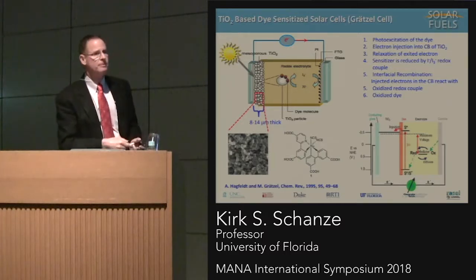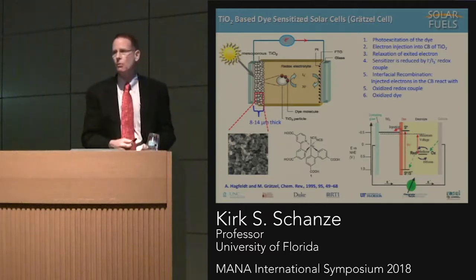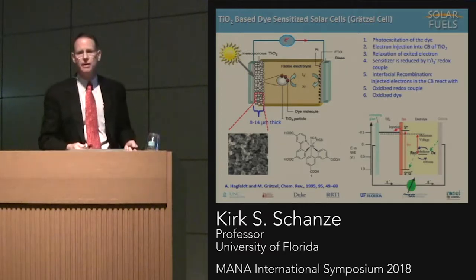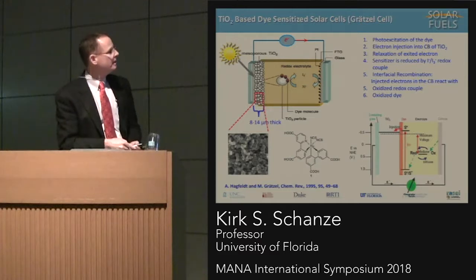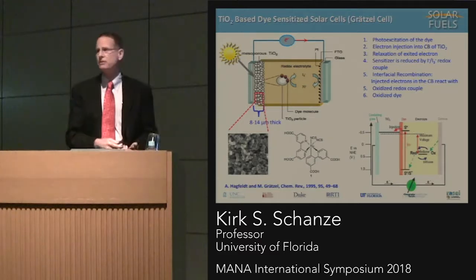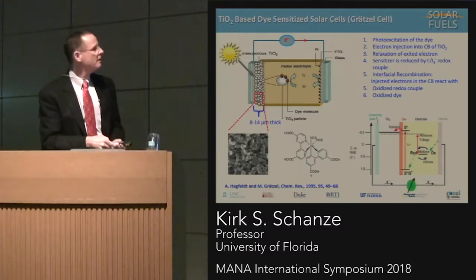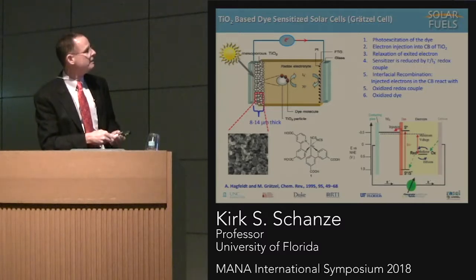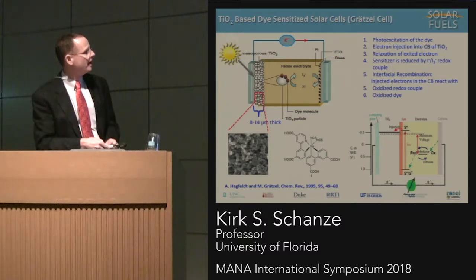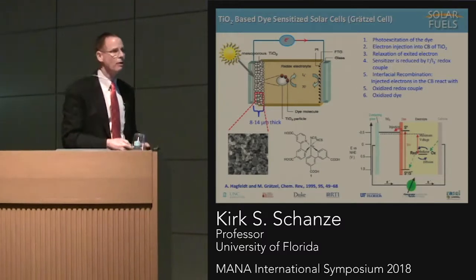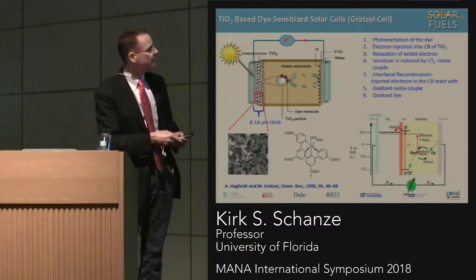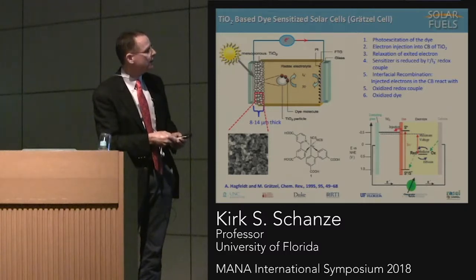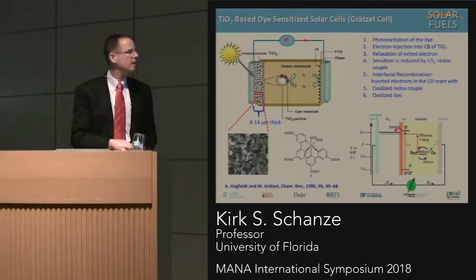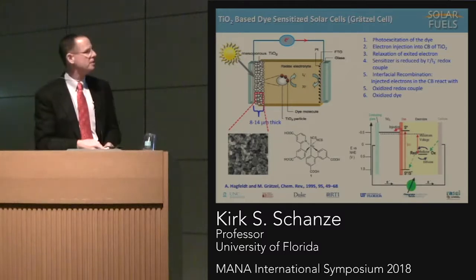And the types of metal oxides that are typically used are wide bandgap semiconductors, so they don't absorb visible light. And so what you have to do is play a trick and use what's called a sensitizer, and that's a visible light absorbing molecule that's surface adsorbed onto the semiconductor, and that molecule does the work of light absorption. When it's activated, the molecule injects an electron into the semiconductor, so that's the charge separation event.